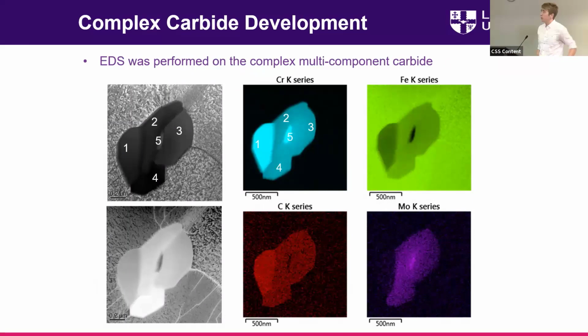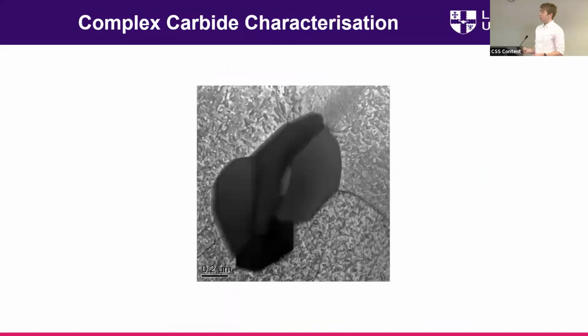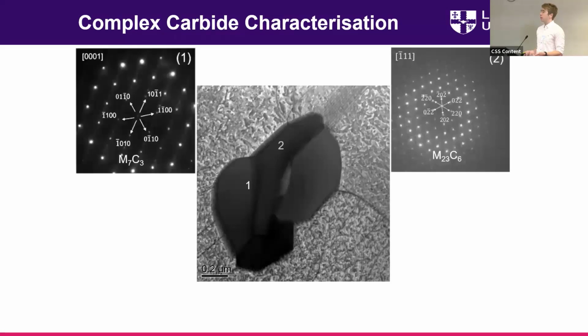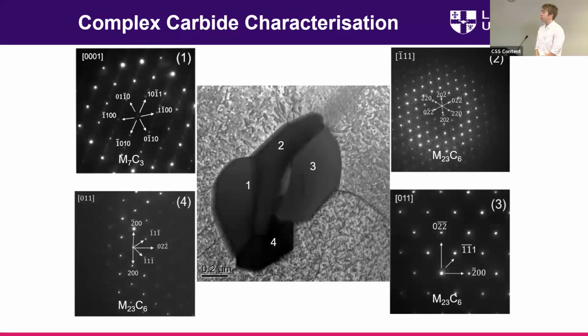areas within the carbide. One of them on the left shows higher chromium concentration, the one that's labelled 1, and then 2, 3, and 4 show a relatively uniform iron and chromium concentration with molybdenum, with 1 not showing any molybdenum concentration. So in combination with the elemental predictions, we went and performed selected area diffraction on these separate parts, and we found that the region labelled 1 was M7C3, and the other sections were all M23C6, which would have been in agreement with what we'd predicted with the modelling and what we'd seen in the previous characterised carbides.